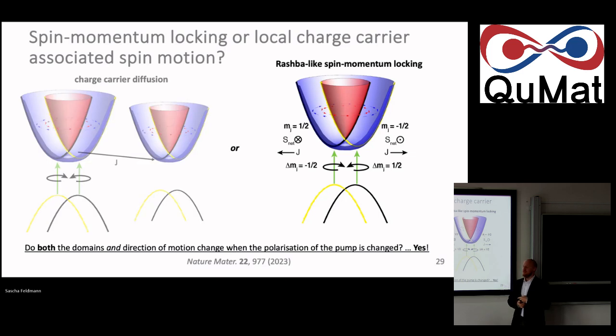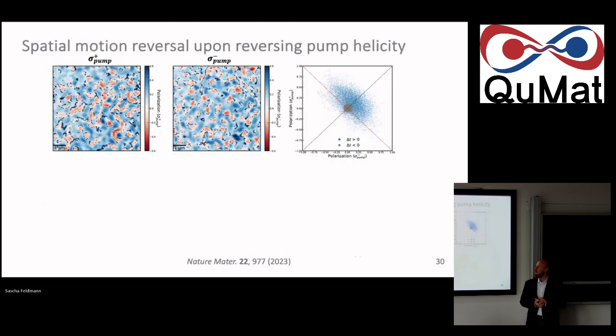So interestingly, and I did really not expect that because I was so skeptical, it does point towards this picture more. So really, changing the helicity of the pump, the sign of all these polarization domains change. So whatever this little snake here in red becomes a blue snake, and so on and so forth. Again, you need the correlation to really make this a robust statement, but the correlation really holds that the domain polarization sign switches.